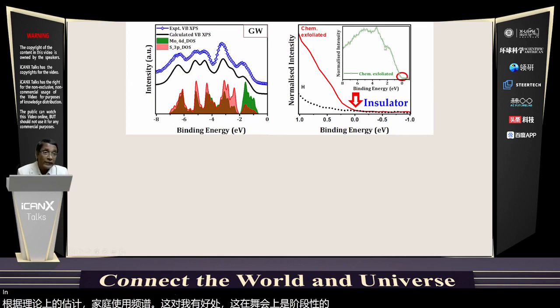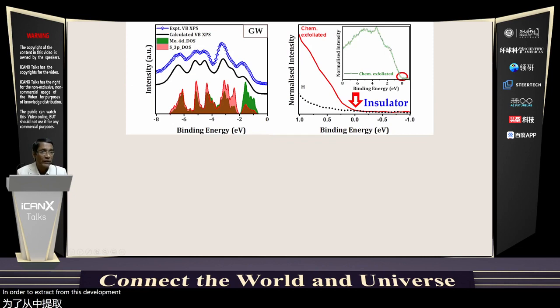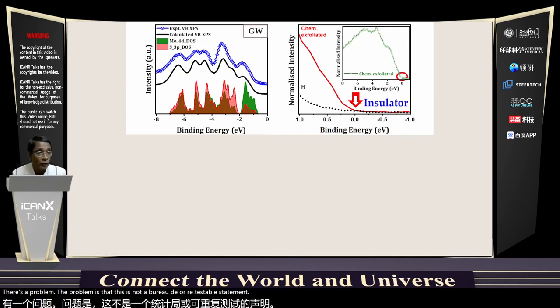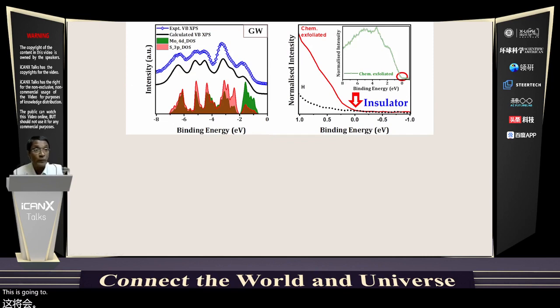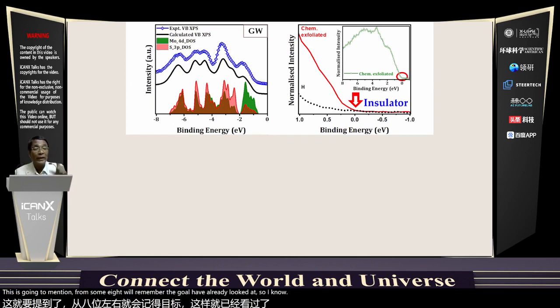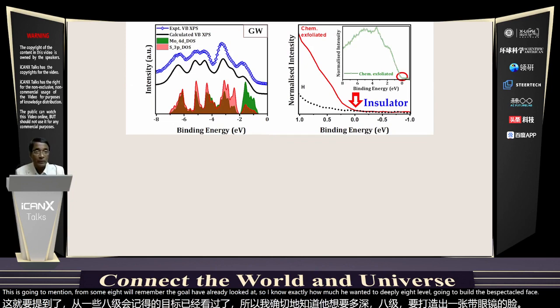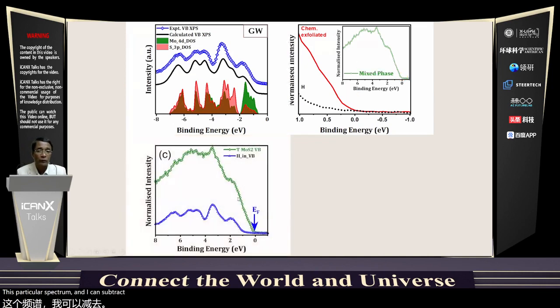In order to extract the valence band spectrum from this, mind you, there's a problem. The problem is that this is not a pure T or metastable state contribution. This has a contribution from some H phase. Remember the core level we looked at, so I know exactly how much, quantitatively, the H phase contributes to this particular spectrum, and I can subtract that out. I know exactly this much of H phase is contributing to this total spectrum.